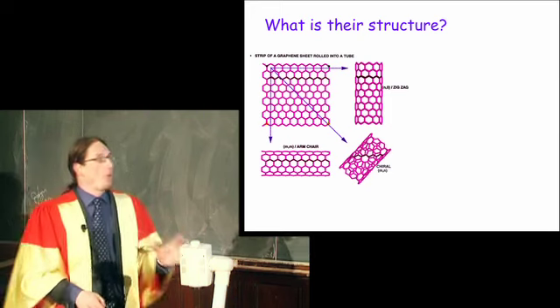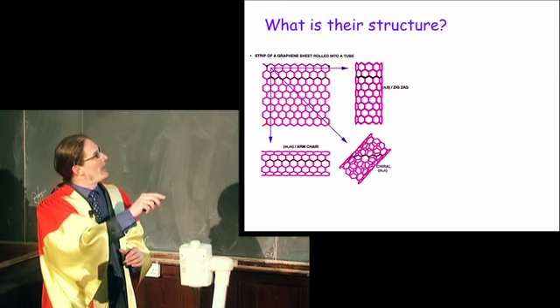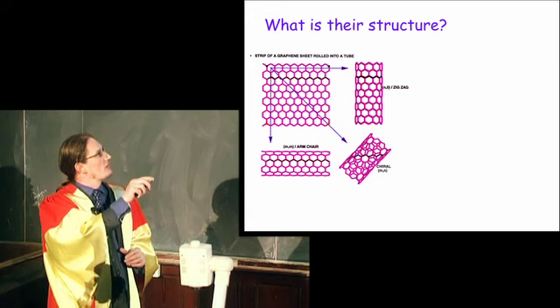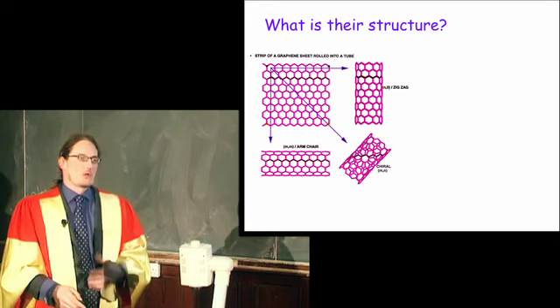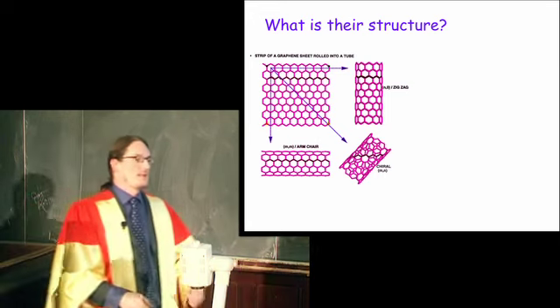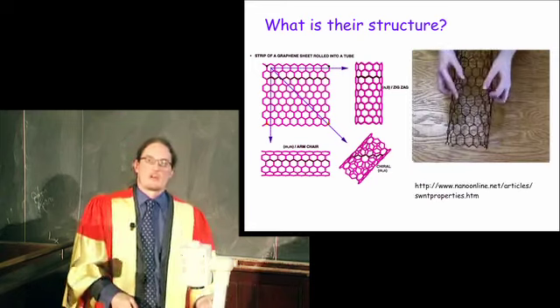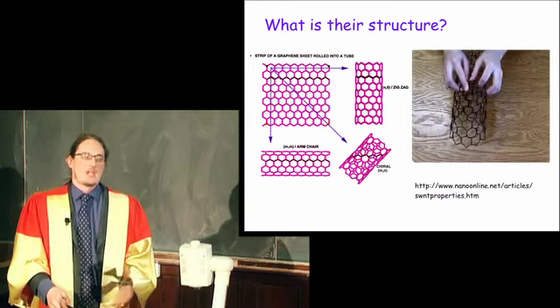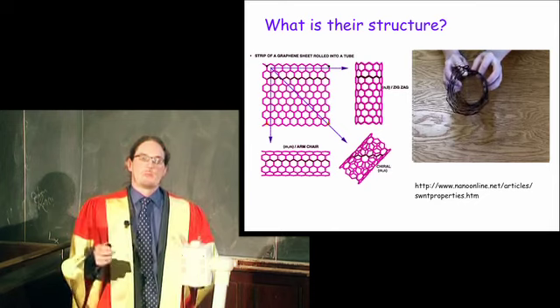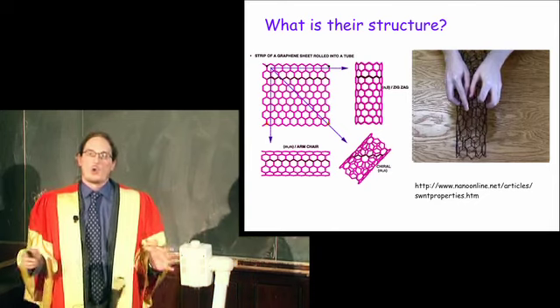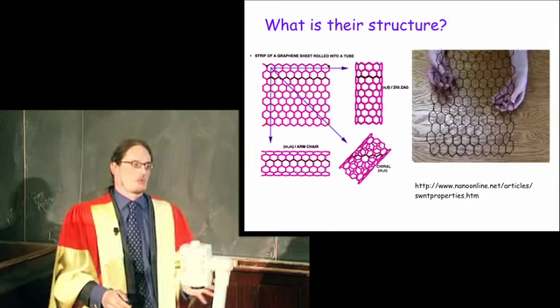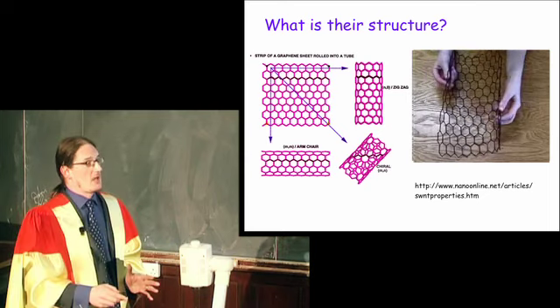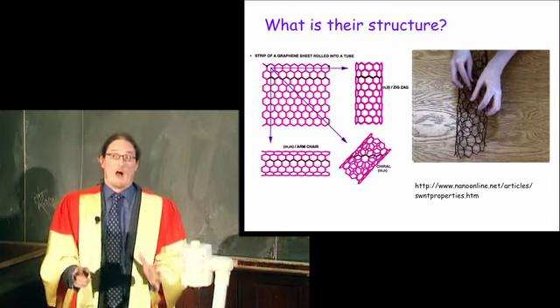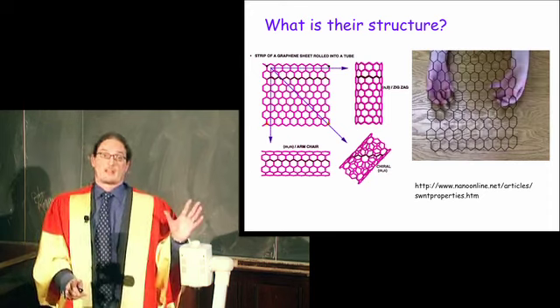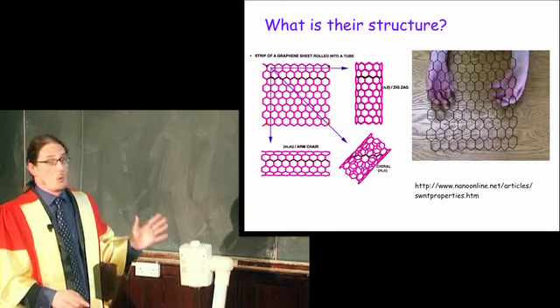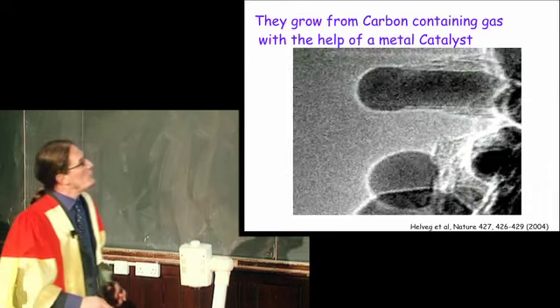Now, the reason that's important is that depending on the angle at which you roll the graphene sheet into a cylinder, you can have materials that are metals, that are semiconductors, and for the semiconductors, they can have a wide range of band gaps. So immediately, just with this simple piece of carbon, you've got the whole range of possible electronic structures. So at that point, people realized very quickly that these things are exciting, because that's the sort of thing the likes of Intel really want to see. So how do we make them?